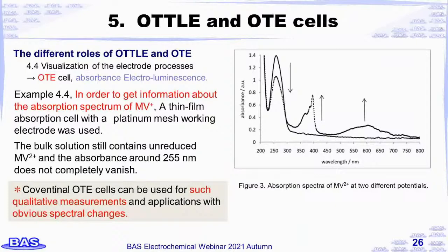Example 4.4. In order to get information about the absorption spectrum of the monovalent cation of methylviologen, a thin film absorption cell with a platinum mesh working electrode was used. The bulk solution still contains unreduced divalent cation methylviologen, and the absorbance around 255 nanometers doesn't completely vanish. Conventional OTE cells can be used for such qualitative measurements and applications with obvious spectral changes.